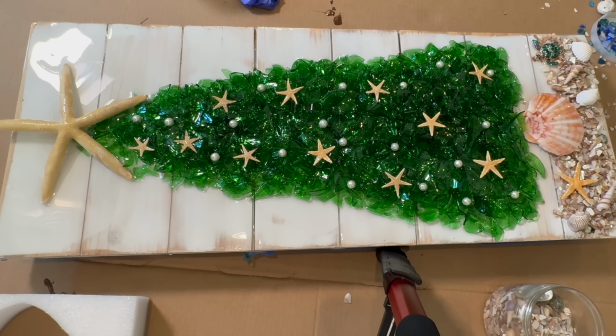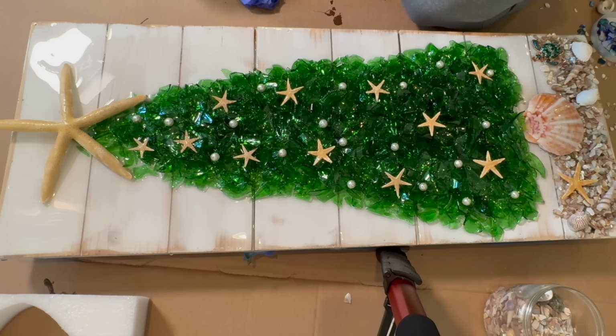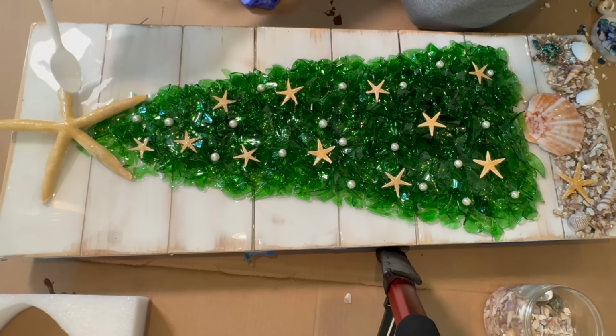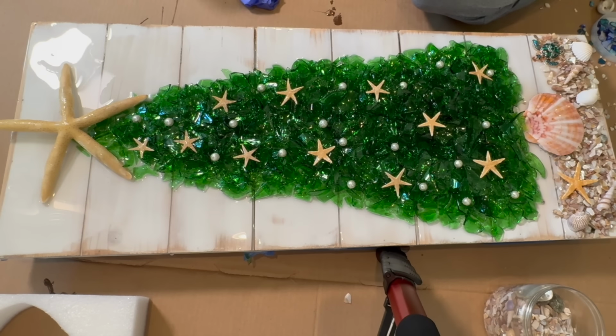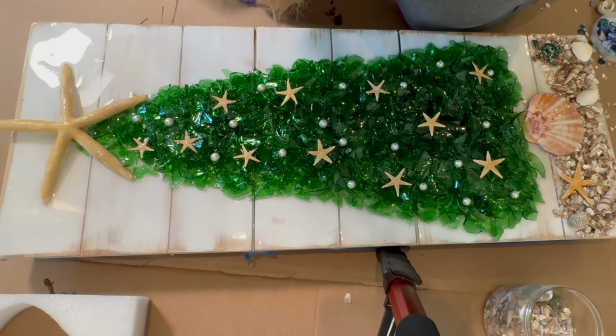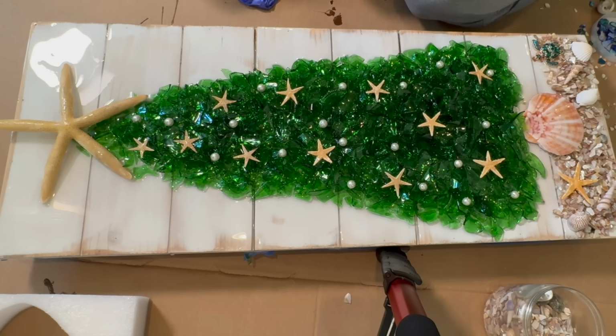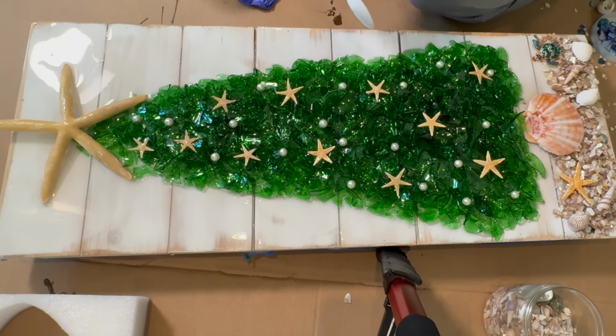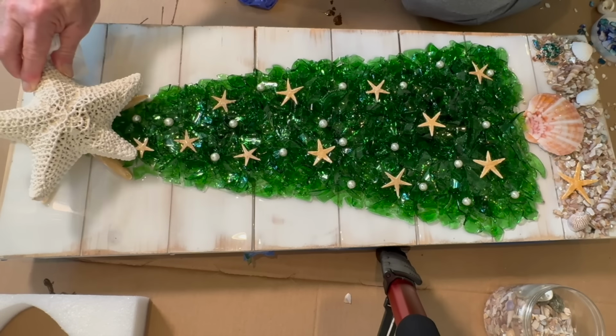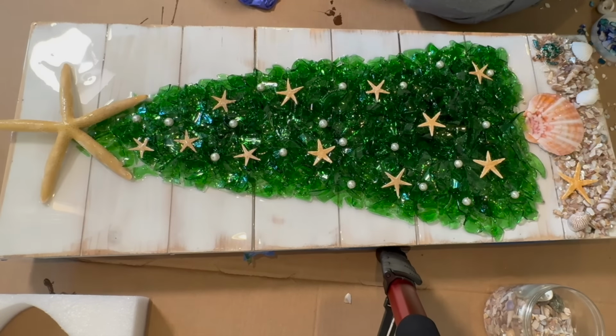So resin sets best at temperatures between 70 and 80 degrees Fahrenheit. It has a 45-minute work time. It's usually hard to touch between 8 and 24 hours and cures completely within 72 hours. I did use the kitchen torch to get rid of the bubbles. It's in your best interest to cover it with a dust cover when done. All resins are different. You need to read the directions for the resin that you are using.